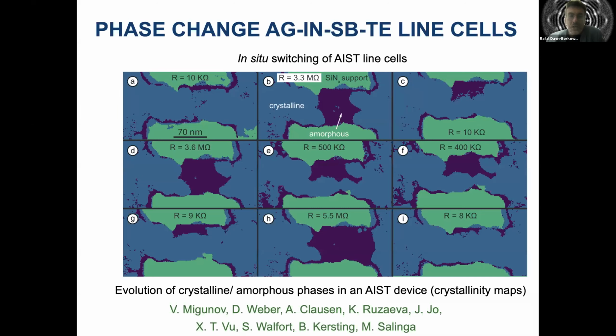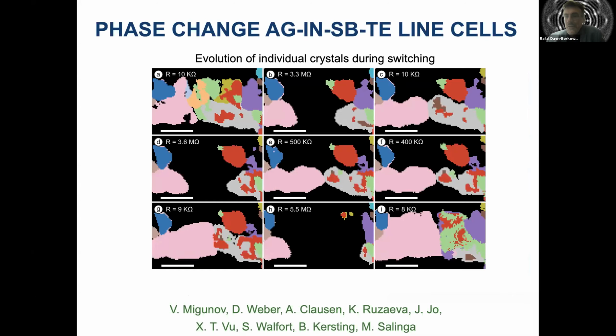So in frame A, the bridge, the device is mainly crystalline, it's a low resistance state. In frame B, there is an amorphous region, a dark blue region in the middle of the bridge, and this is a high resistance state, and so on. But because we're recording diffraction patterns point by point, we can group together diffraction patterns which look similar, and we can look at the evolution of individual crystallites during switching and color code every region which is crystalline, which corresponds to the same crystallographic orientation. And in this case, as the device is switched between low resistance and high resistance states, you can see which crystalline regions remain in the same orientation as they are switched from cycle to cycle, and in which cases the switching is not reproducible.